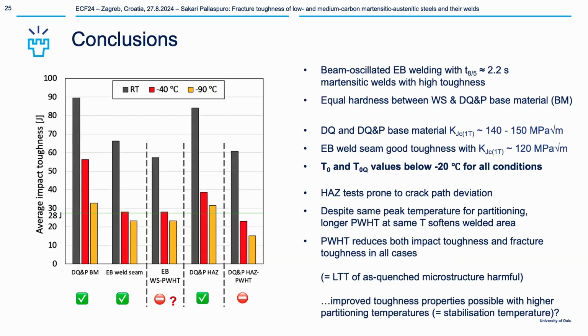Also for these electron beam welded values, despite the carbon equivalent being around the level of 0.7, they are still valuable, at least with these conditions. But the challenge is that if you need to apply the post-weld heat treatment, it will actually ruin the properties that you achieved, at least with this alloy design.